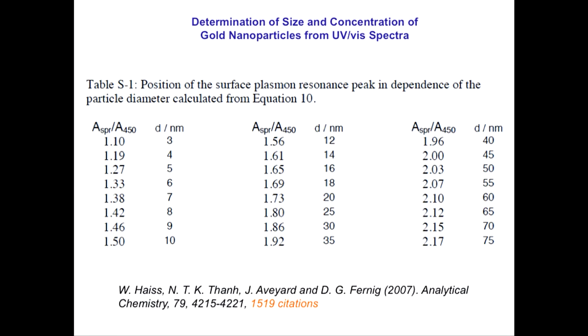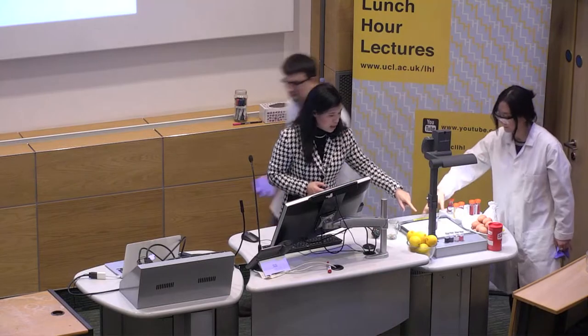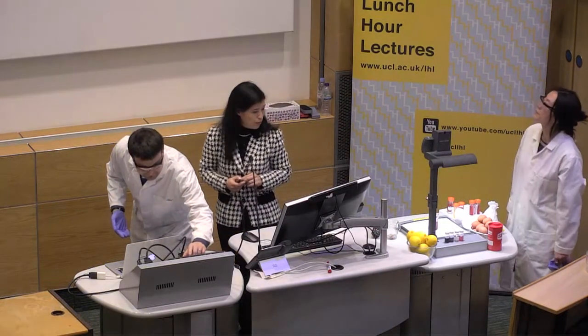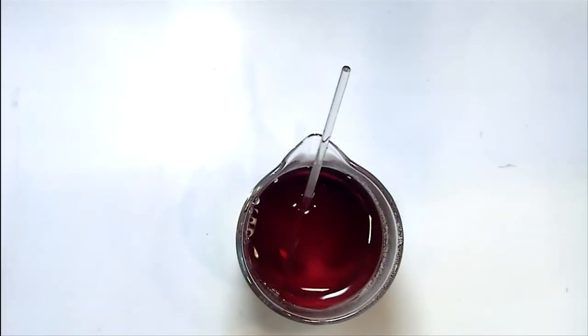So you take the absorption at the maximum and divide it by the absorption at 450, and then use this ratio to determine the size of the nanoparticle. So it's very simple to determine the size of the nanoparticle. And you can see now that the color has already changed. It changes very quickly, and hopefully you can see a beautiful ruby fluid there, so we can make gold nanoparticles very quickly using gold salt with lemon juice.